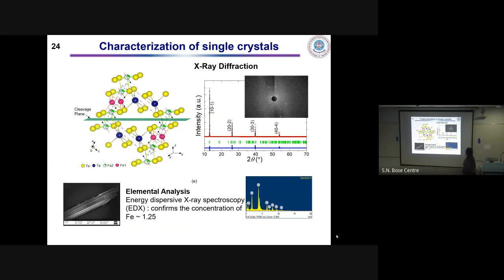Before moving on to the results, I would like to give the characterization of the single crystals. Here you can see it has a very unique magnetic structure also. The Fe1 atoms comprise a two-leg ladder kind of structure. The Fe1 forms zigzag chains and they are ferromagnetically coupled to each other. The Fe2 atoms are also ferromagnetically coupled to the Fe1 atoms within a single ladder. However, the interladder coupling is antiferromagnetic in this system. So it has an interesting magnetic structure, which will help us in understanding the magnetotransport property.